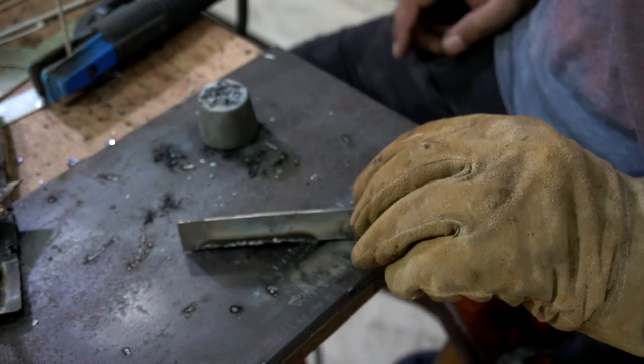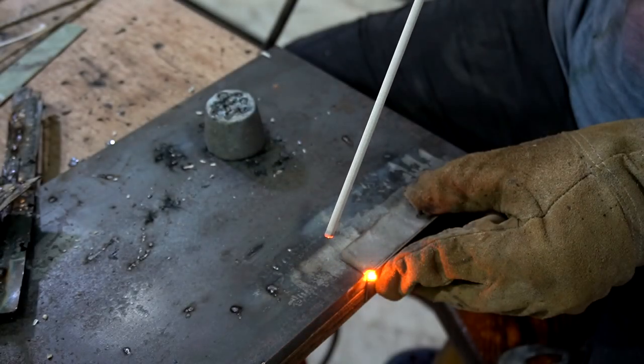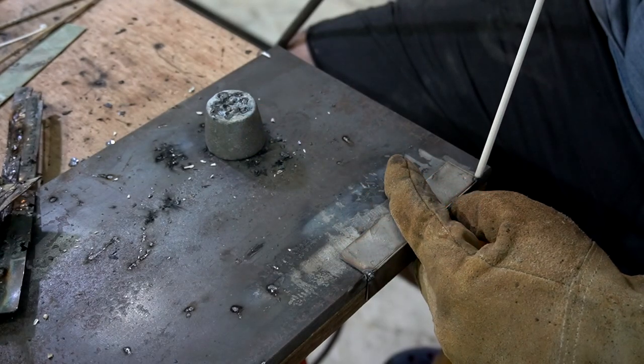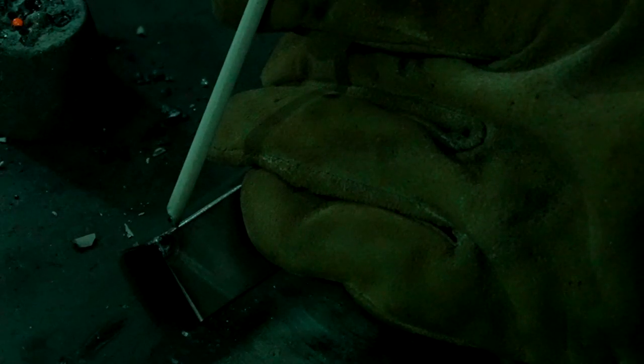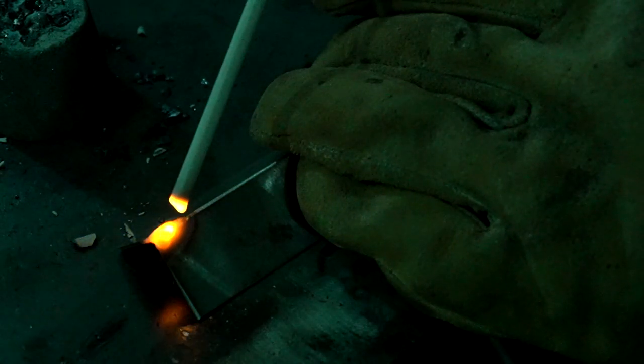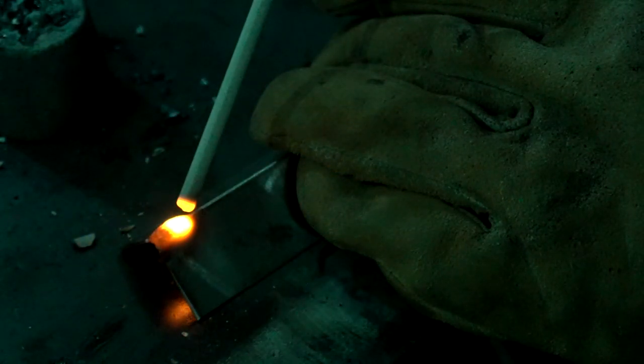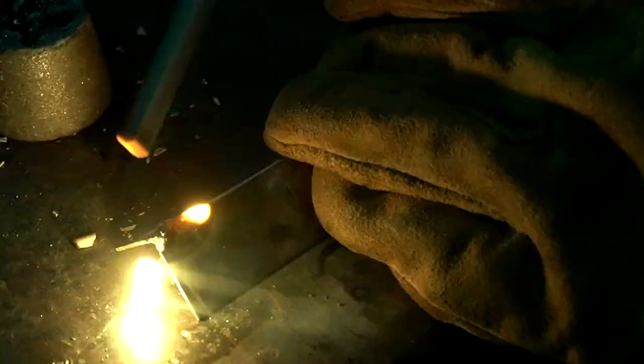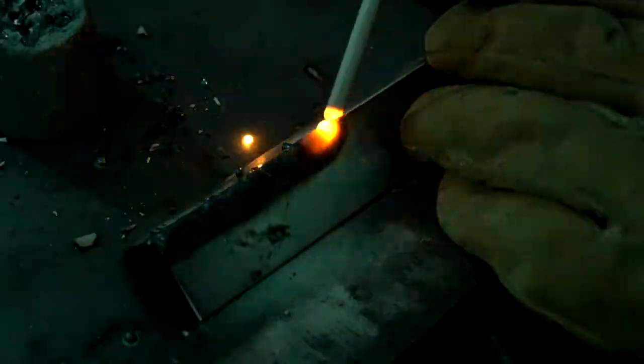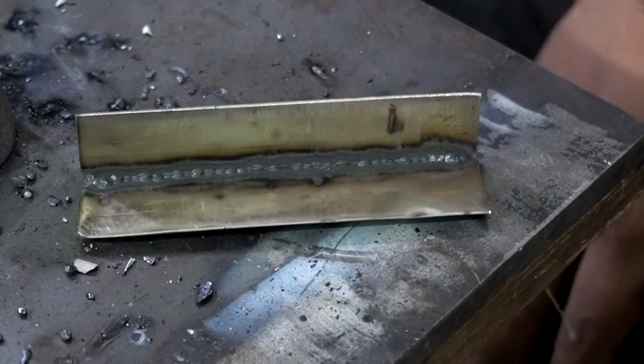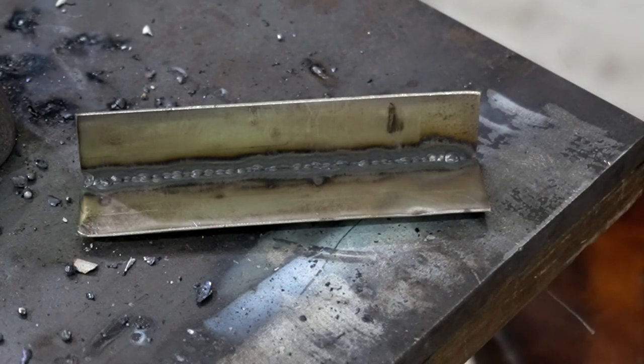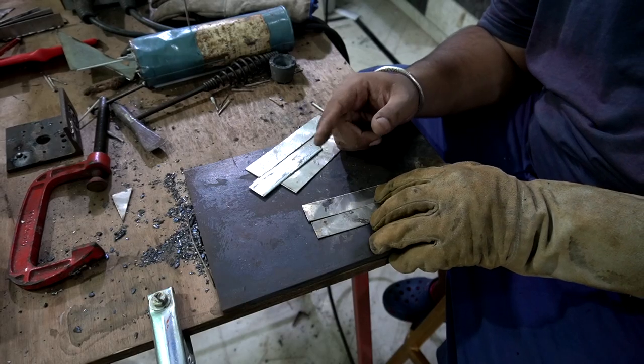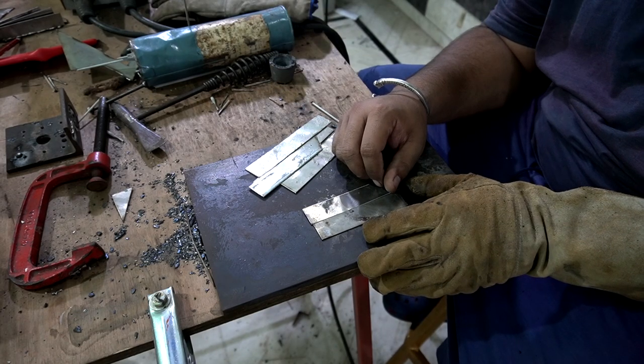So the third one, I am again going with the 45 amps current setting, and the same technique which I previously did, and in this case the weld beads are quite thicker compared to the previous two attempts. I have some experience with 2.4 millimeter electrode, so it wasn't difficult for me, but definitely the chances of blowholes are quite high. And now I'm going to show you how flat weld looks with all the three different electrodes having different settings.